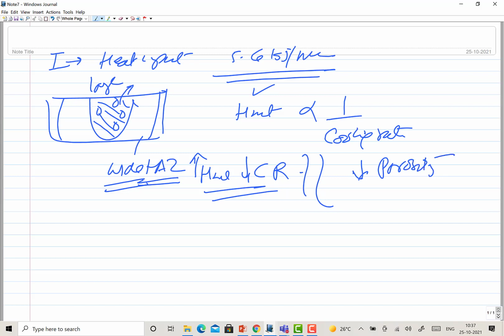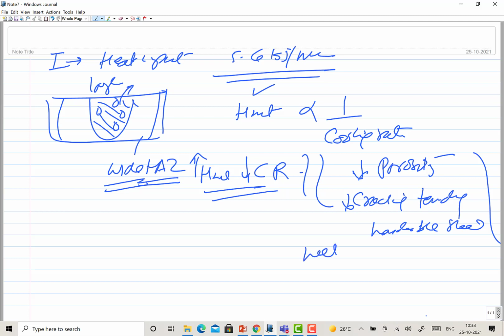Because of the low cooling rates and longer solidification time, gases will have enough time for escaping from the weld metal, and therefore porosity is very limited. On the other hand, the cracking tendency of the weld is less, especially of the hardenable steels. So hardenable steel cracking tendency is reduced because of the low cooling rate, and the porosity tendency is also reduced. Since there is enough time for weld metal to solidify, the weld bead is very smooth. Okay, a very smooth weld bead is produced.